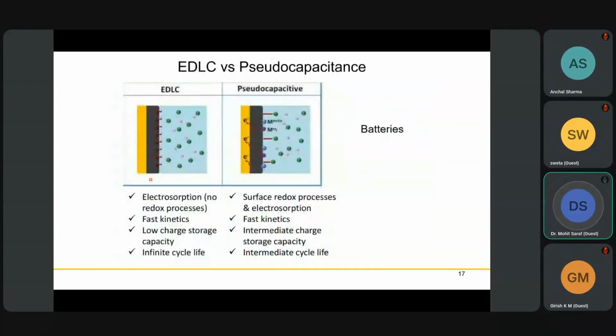When we compare EDLC and pseudocapacitive systems, in EDLC we have electrosorption with no redox process, but in pseudocapacitive we have this redox process, and it is very fast. Both are very fast, but the amount of charge storage in EDLC is slightly low, while in pseudocapacitive it is more. You can run EDLC supercapacitors for millions of cycles, and pseudocapacitive systems such as MXene can also run for millions of cycles, but still, compared with EDLC, it will be low.